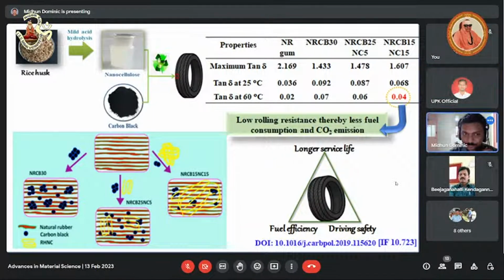Okay, thank you. So this is another work that our group has conducted with nanocellulose, and this paper is also published in Carbohydrate Polymers. We have prepared nanocellulose from rice husk by alkali treatment, bleaching, followed by oxalic acid hydrolysis. The nanocellulose was mixed with carbon black, using the same procedure that we applied before. And here you have the result.